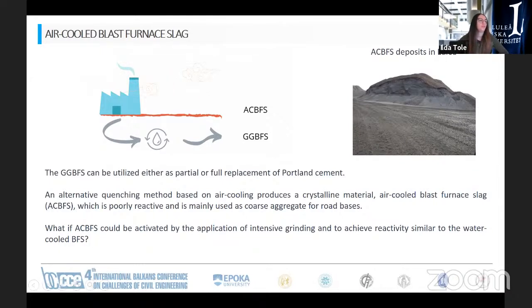The difference between these two materials is the reactivity, because as I mentioned before, the ground granulated blast furnace slag is already proven to be used for the replacement of cement, and it's an amorphous material due to the rapid quenching with water, while the air-cooled blast furnace slag method produces a crystalline material. So actually it's really poorly reactive and is mainly utilized as coarse aggregate for road bases. So again, these are unused sources that are just deposited in some uninhabited area.